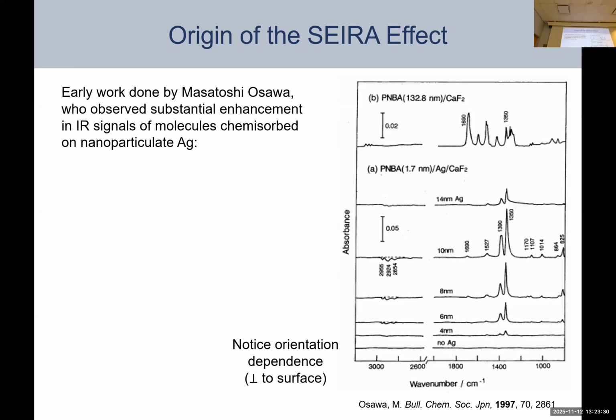Okay, and then they start looking at deposition of this molecule on top of these nanoparticulate silver surfaces. So here, this number is going to tell you the size of the nanoparticle of silver, okay? And so same loading of the nitrobenzoic acid. But you can see that if you have no silver present, you see absolutely nothing for really small loading of the molecule, right? And that's what you'd expect. Everyone intuitively knows you have to put enough material on your ATR in order to see a signal, right? So if it's really, really low coverage on a surface, we're not going to see a signal. But as soon as we start having larger and larger nanoparticles, you start to see really enhanced signals.